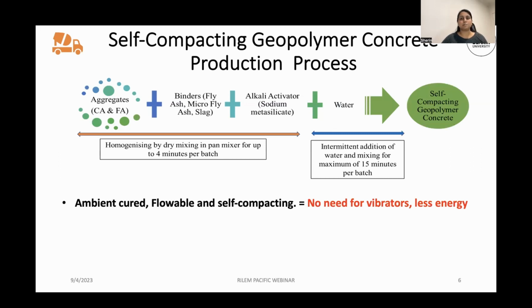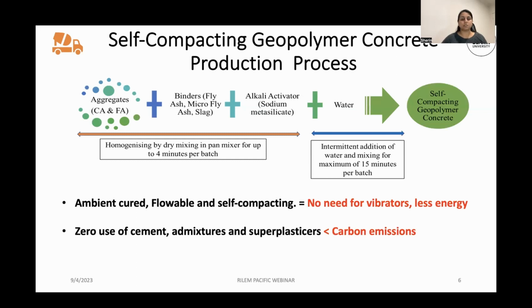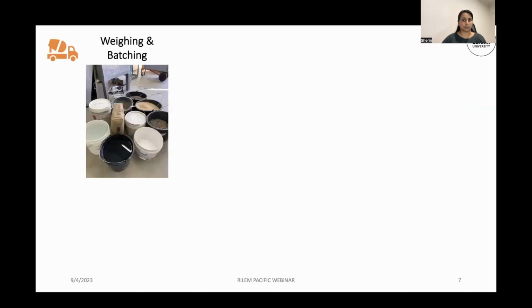This means that this type of concrete will not make use of any vibrators and thereby uses less energy. This is also a zero use of cement, admixtures, and superplasticizers. This is directly contributing to reduced carbon emissions. Finally, in the way of strength, we have found that this self-compacting geopolymer concrete reports 40 MPa compressive strength at 28 days, which is greater than the normal M32 concrete, and thereby it can be classified as a structural concrete.